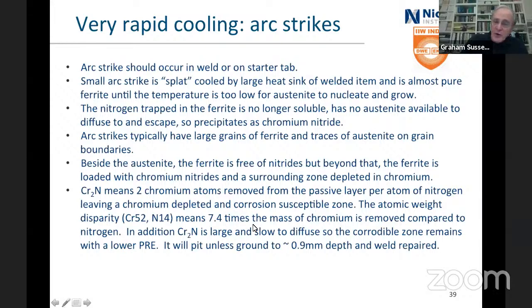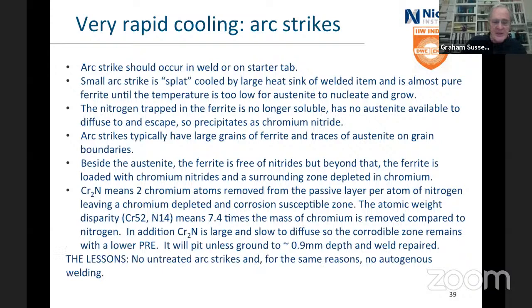And this work found that you had to grind almost 1 millimeter depth underneath your splat to actually get to the bottom. And how do I know that? Because it's a nice little thing that Kotecki put into an item in the Welding Journal, American Welding Journal. So the lesson: don't leave arc strikes untreated, don't do arc strikes. And if there is an arc strike, treat it, get rid of it, gouge it out and repair it. For the same reason, don't go doing autogenous welding on duplex stainless steels.